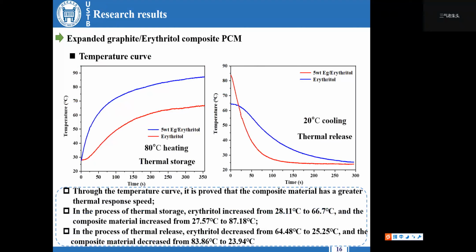In order to more intuitively quantify the thermal response speed of the composite material, the relationship between the surface temperature of the sample and time was plotted. It can be seen that the composite material has a greater thermal response speed. In the thermal energy storage stage, erythritol increased from 28.11 to 66.7 degrees, and the composite material increased from 27.57 degrees to 87.18 degrees. In the thermal energy release stage, erythritol decreased from 64.48 to 25.25 degrees, and the composite material decreased from 83.86 to 23.94.